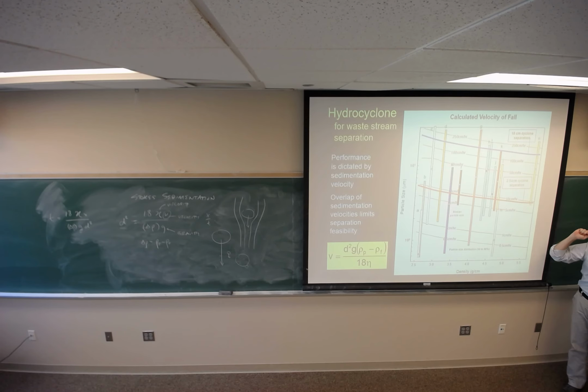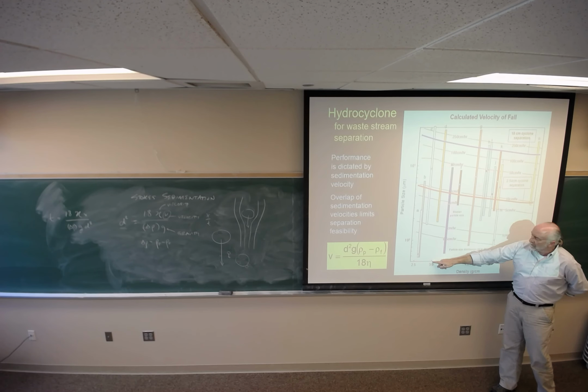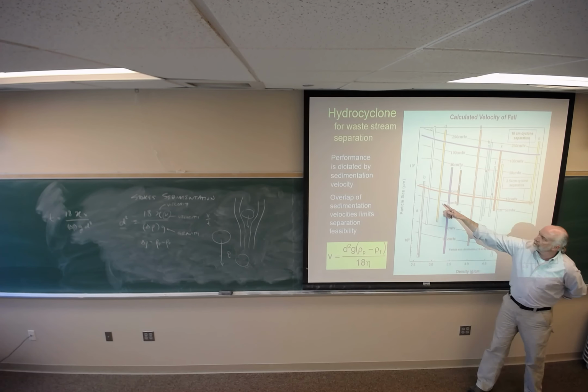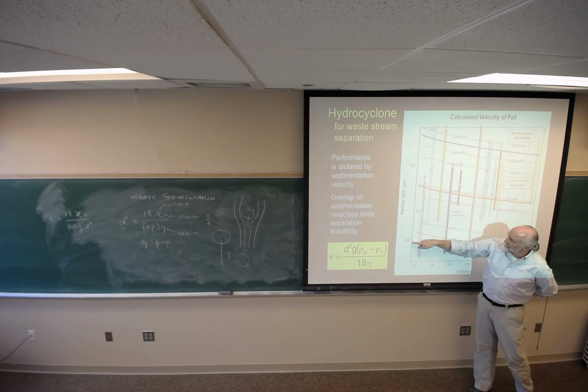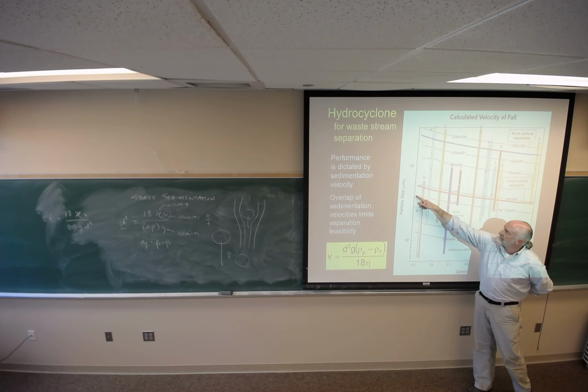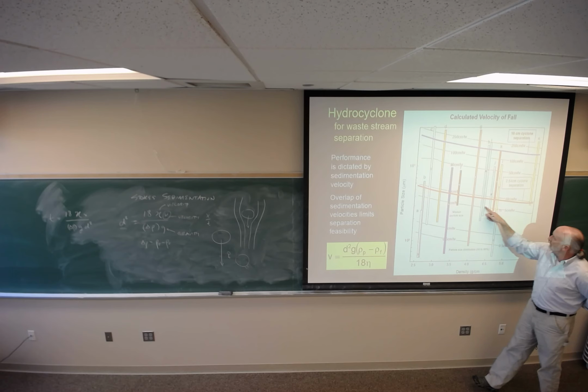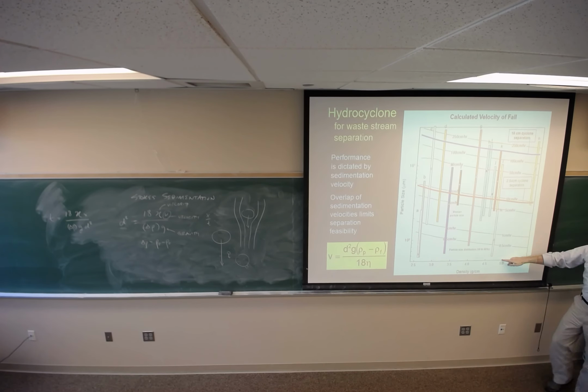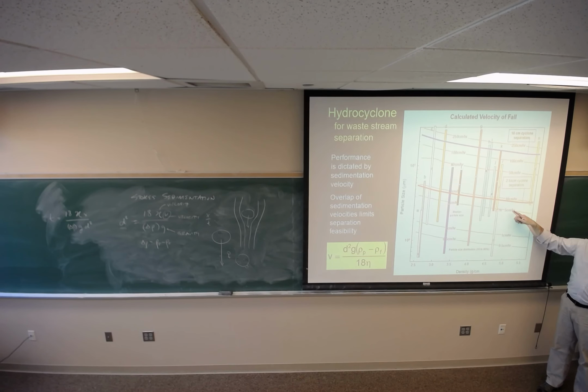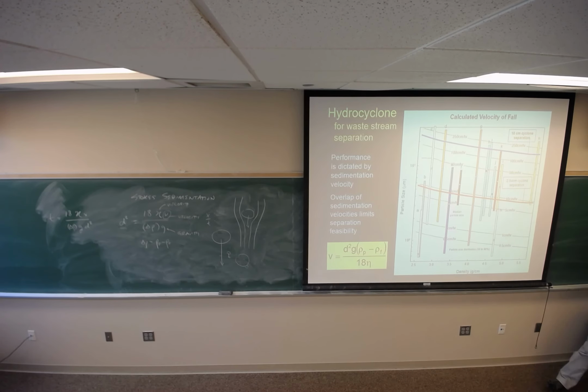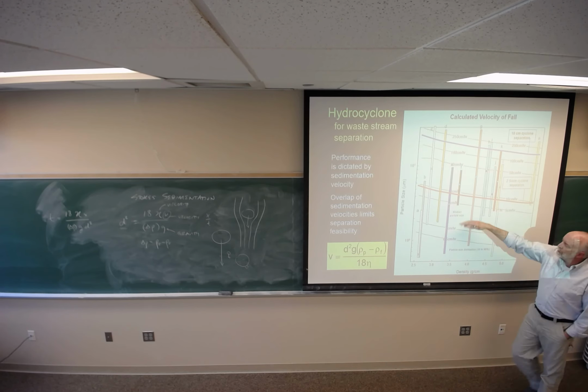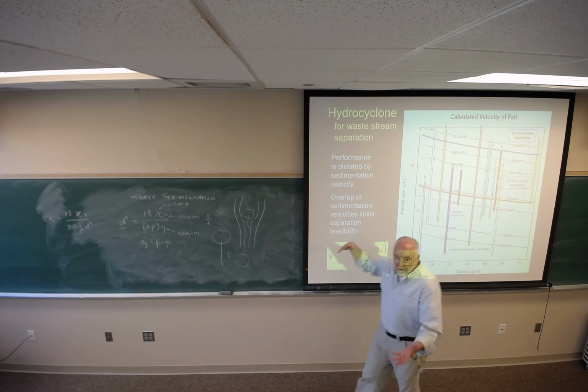Okay, so if I was at a density of 3 grams per cubic centimeter, and I have a particle size that's roughly, say, let's see, 1, 2, 3, 4, there's my sedimentation velocity, it would be 5 centimeters per hour. If I was at 5 grams per cubic centimeter and somewhere around 0.3 microns, they have the same sedimentation velocity. Well, that doesn't seem like a big difference. But what you see is that these particle size distributions that are drawn here overlap a broad range of sedimentation velocities.